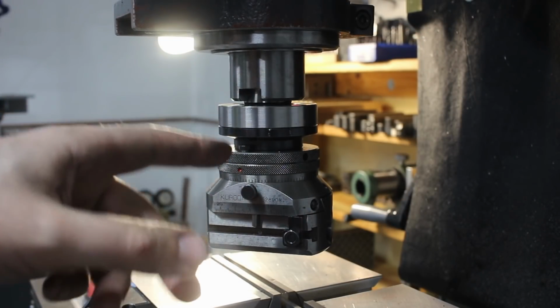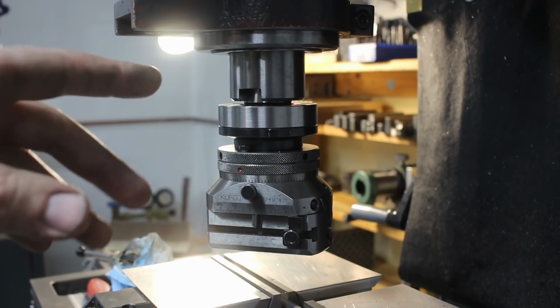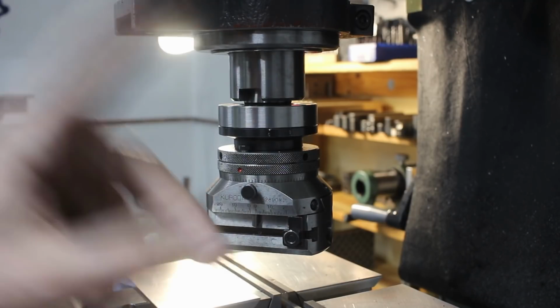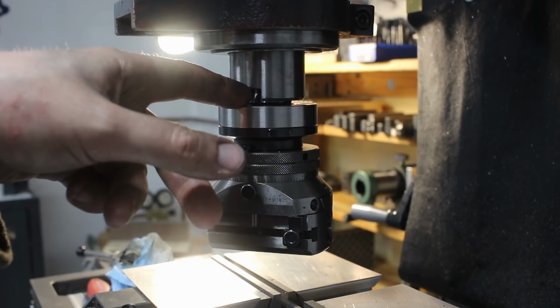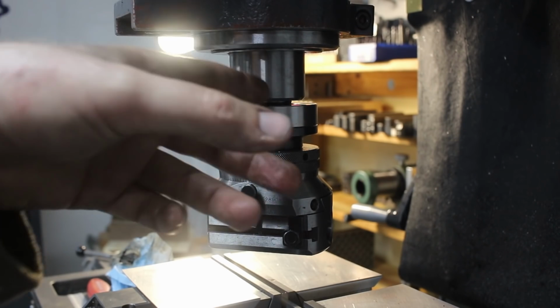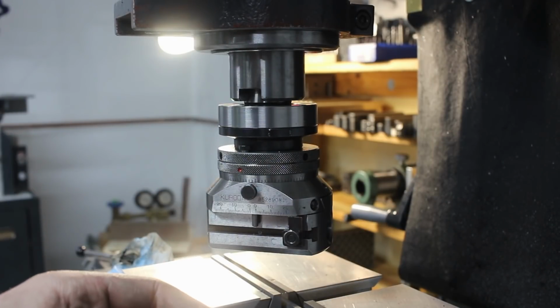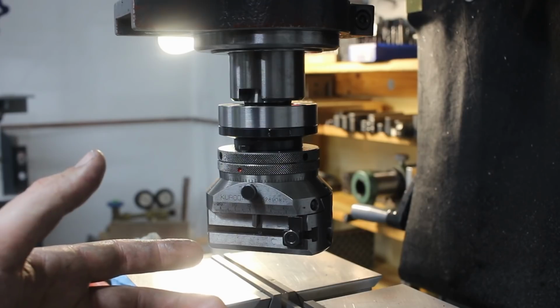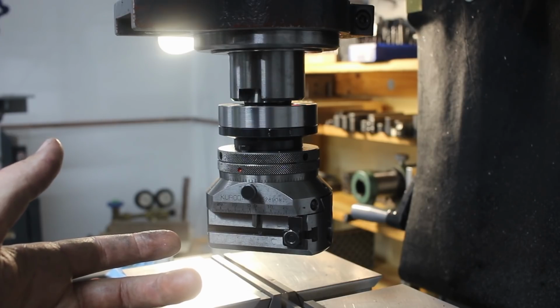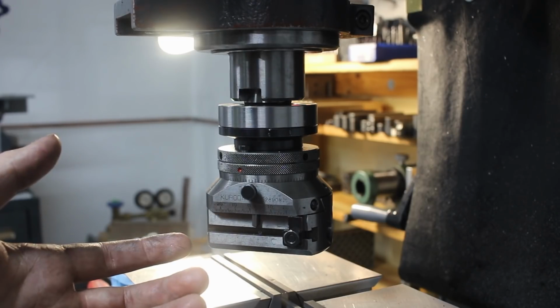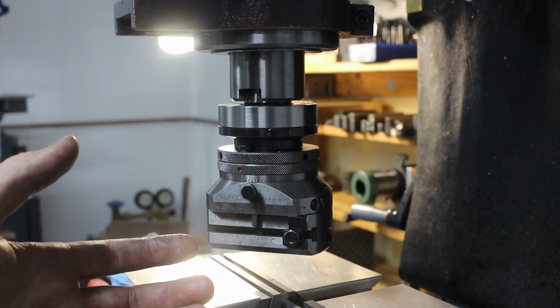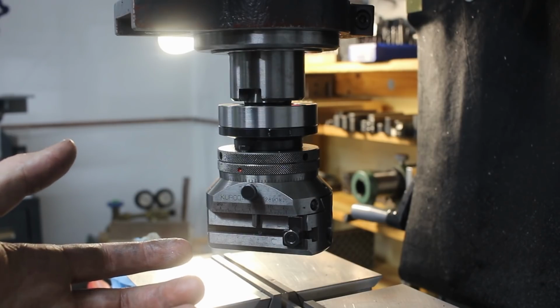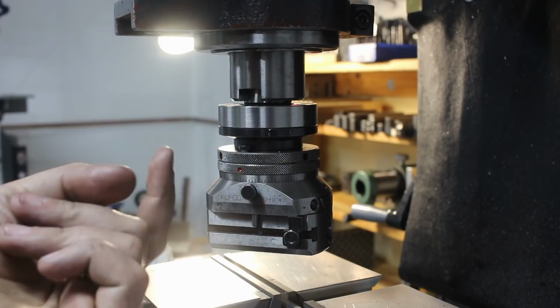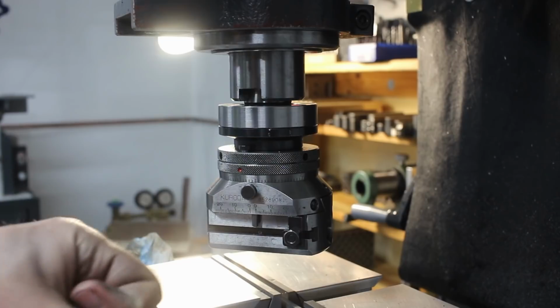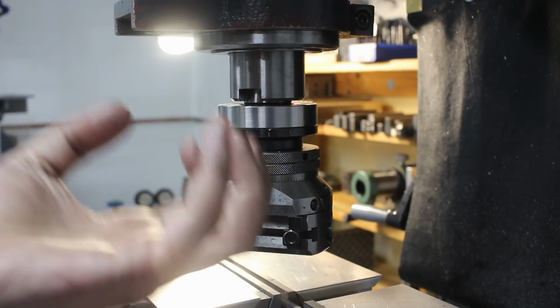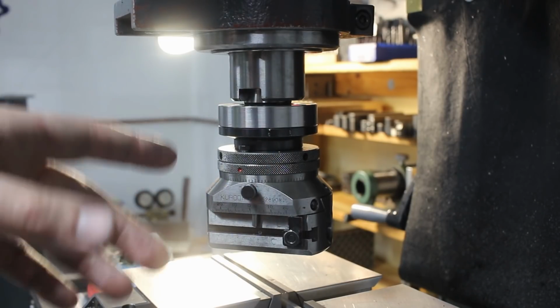Yes, because ISO 30, the steep taper in these machines, without drive dogs, relying alone on friction with a threaded drawbar, note that I said threaded drawbar, can transfer a few kilowatts of spindle power just through the fit of the taper. If you ever ran a Deckel FP1, FP2, FP3 manual mill, it's SK40, an ISO 40 taper, and most tools don't use drive dogs. The collets for end mills go up to 32 millimeters, and those run without drive dogs because a drawbar with a thread pulls the taper way stronger into the spindle, because people grunt down on the drawbar like crazy, and just the friction and the fit will transfer huge amounts of power.